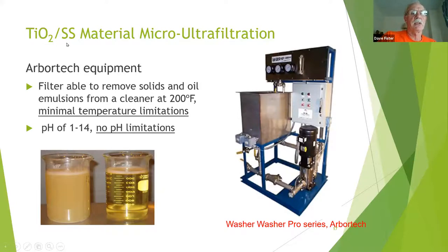This is a titanium oxide stainless steel matrix micro/ultrafilter. It's somewhere in between microfiltration and ultrafiltration in terms of particle size. It's made by a company called Arbortech, which was recently purchased by Hubbard Hall. The filter is able to remove solids and oil emulsions, and it can go as high as 200 degrees Fahrenheit, which means you can have a hot tank being filtered while you were running your operation. Extremely pH tolerant, 1 to 14. So caustic solution, no problem.